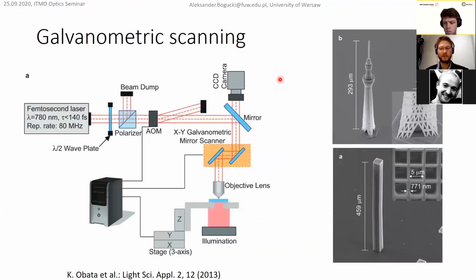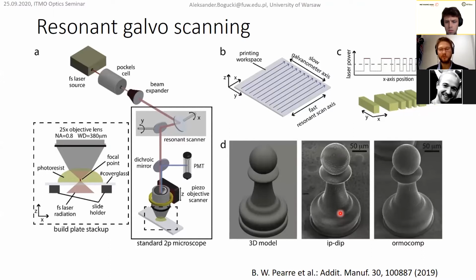But there are a lot of other concepts which are even faster. Some have advantages, or these are also disadvantages. So for example, instead of moving the whole sample on a piezo stage, you can move the laser beam using a galvanometric mirror scanner, and then you can improve the writing speed by one or two orders of magnitude, but you need a more powerful laser, of course. And you can see an example of a really impressive high aspect ratio structure, which is 5 micrometers wide and almost 500 micrometers in height. And people are improving it even more.